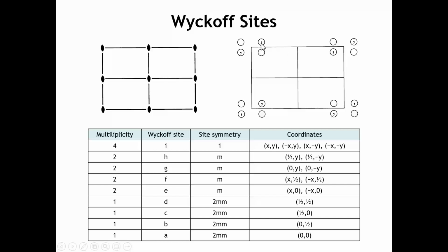The ones that have a comma in them, that means that the handedness is switched. So if you have an object with chirality, say for example like a hand, and you reflect through a mirror, you're going to get the opposite-handed representation of that object. Whereas if you rotate by a twofold rotation axis, you would not change the handedness. Okay, so that's what this diagram shows us.